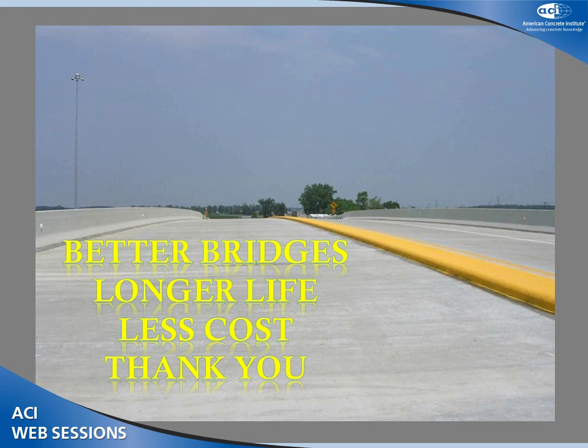It's not needed. If you look at it this way, I showed you the wearing surface, the 15, 20-year-old wearing surface here. If we're not seeing a deterioration of the wearing surface, that tells you a lot in regards to the resistance, the porosity. If you're not seeing that breaking down, and we all know what happens there. In Ohio, they put a lot of salts and a lot of chemicals on there. So we're not seeing that. And if we don't have the cracks, you don't have the migration of the water to the reinforcing.